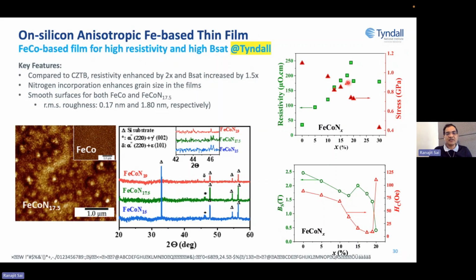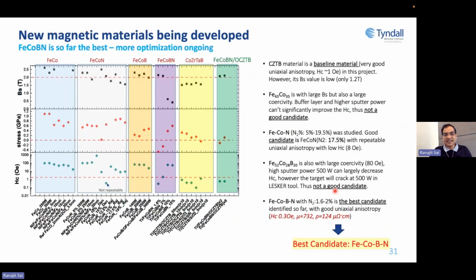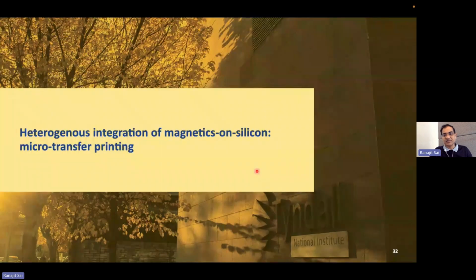And that means it will not be prone to delamination or structural issues, and that's great. And it has a BSAT value which is very close to 2 Tesla, and that was amazing. So in that sense, this FeCoB-based material can be very useful. And we have tried various sister compositions of that, and we have found that the FeCoBN based material is one of the best candidates to explore for future generation of magnetic materials for thin film application.